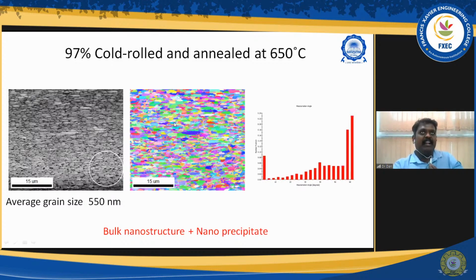Because in this Cantor alloy, they found that below 700 degrees, if you heat treat the sample, it will form some chromium-rich precipitate. In the left side microstructure you can clearly see the precipitation, a little bit of sigma phase, right? On the right side you can see the misorientation angle distribution. Based on that, I got a grain size in the range of 550 nanometers in this process with precipitation. Precipitation also increases the strength of your material. That is my idea, so I purposefully induced the precipitation in the metal.